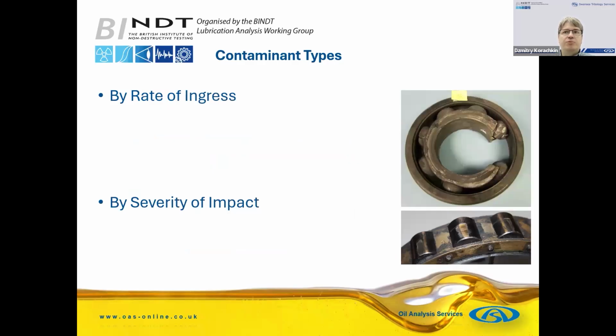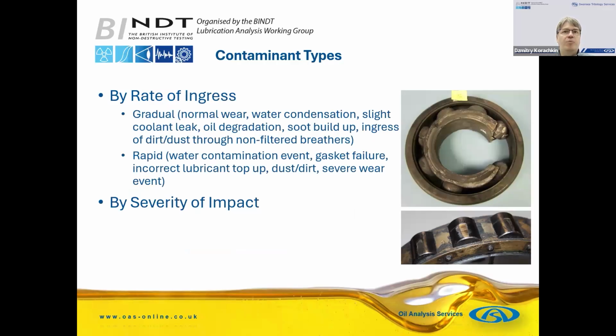We can look at contaminants by rate of ingress. Is it gradual? So normal wear particles, maybe water ingress through condensation, slight coolant leak, the degradation of oil, the buildup of the insolubles, soot buildup, and then ingress of dust and dirt, perhaps through breathers which don't have filtered breathers on, or it could be rapid. So unknown water contamination event, somebody was pressure washing something and lots of water got in straight away, or there's a head gasket failure in an engine, or somebody just put in the wrong lubricant top up, and immediately we have a bulk change, which is very rapid. Ingress of dust and dirt in a more rapid way, or severe wear event which generates a lot of wear.